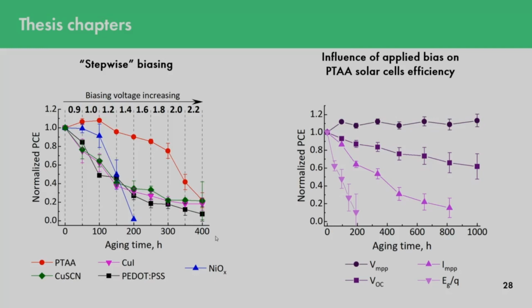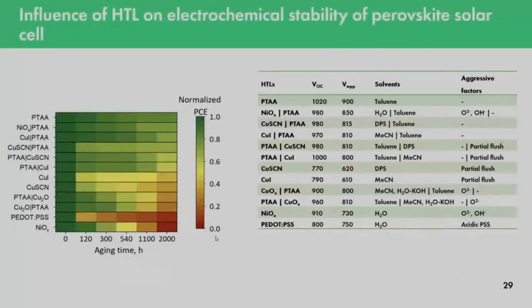So we performed these experiments for PTAA HTL solar cells. And according to this experiment, we decided to choose the voltage of 1 volt, which is close to the open circuit voltage of PTAA devices, and actually close to all other kinds of devices. So we checked a huge amount of different hole transport materials and also their combinations, to check how introduction of polymeric PTAA between perovskite and oxides and salts can influence the degradation of material.